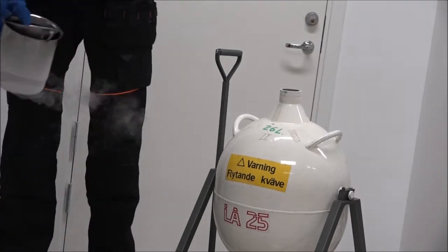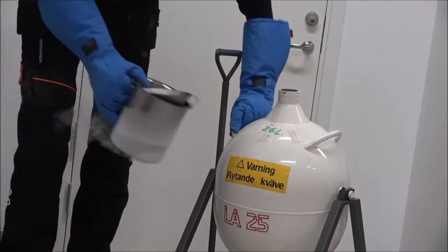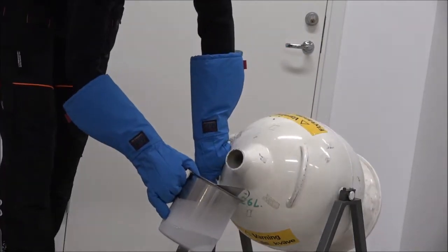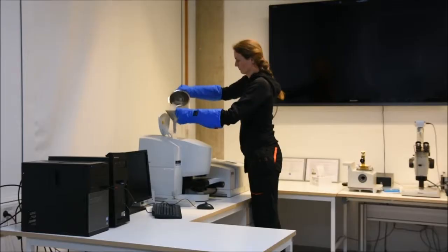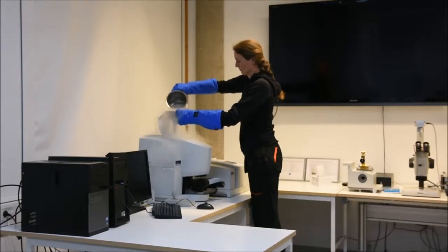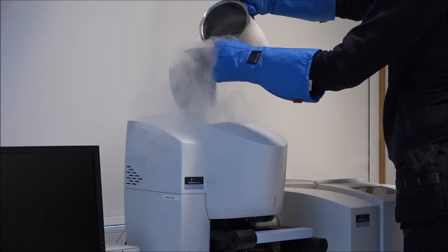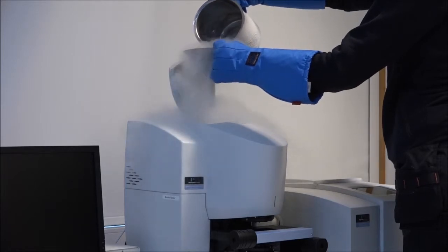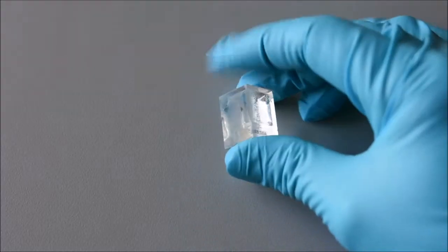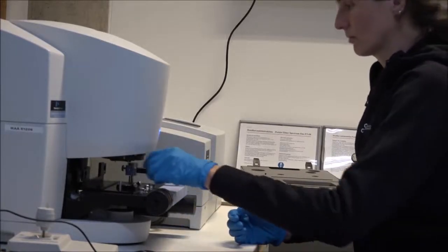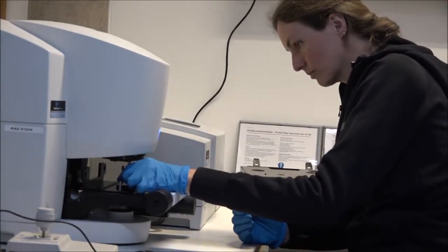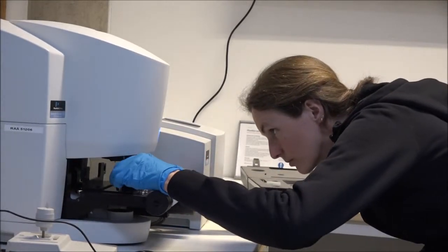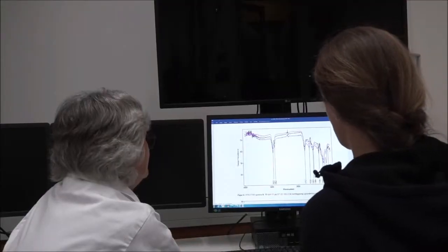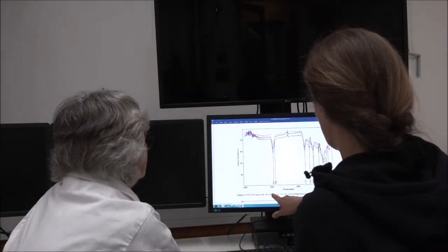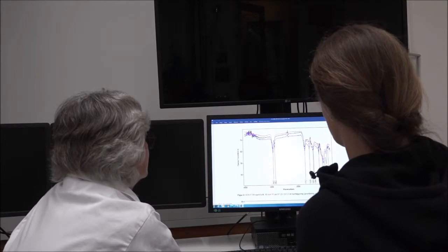To investigate the binder in the paint, ATR-FTIR mapping was used. To run the instrument, the detector is first cooled with liquid nitrogen. A cast paint sample is placed in the FTIR instrument, and the results indicate that both the primer and painting are done with an oil-based binder. The presence of lead, and also kaolinite, usual in primers, is identified.